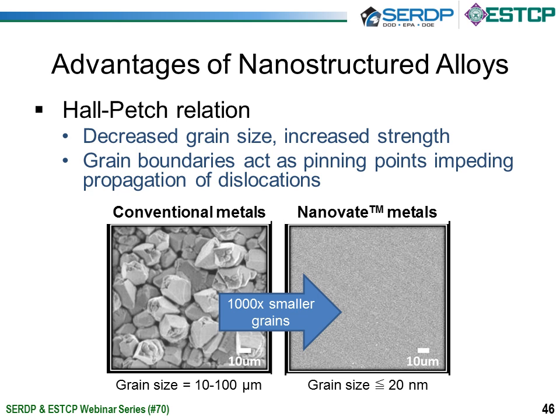This is a relationship that's been known for quite a number of years. I think it was discovered back in the 1940s and 1950s. But with the advent of a lot of nanograin materials, it's been well demonstrated that the optimum grain size is probably around 10 to 20 nanometers. If you go much smaller, there are no further benefits.